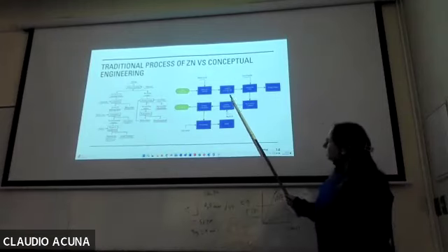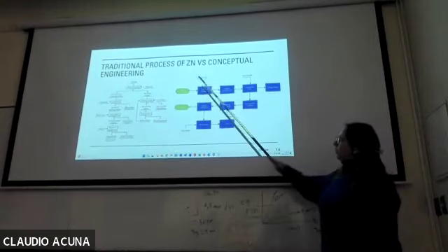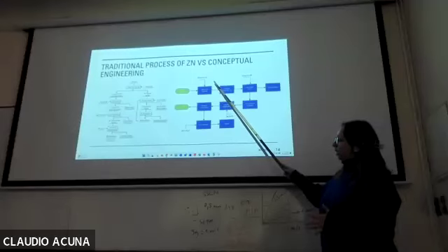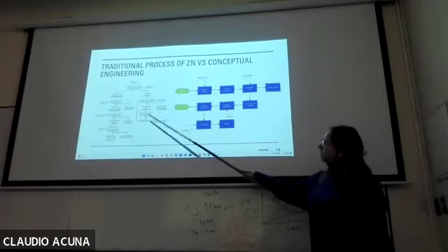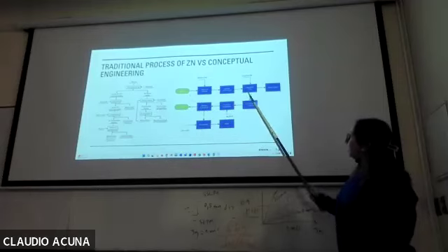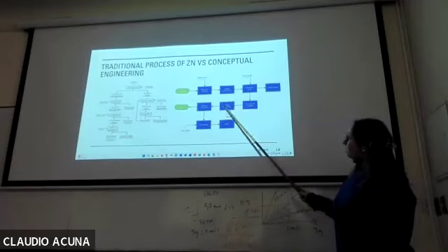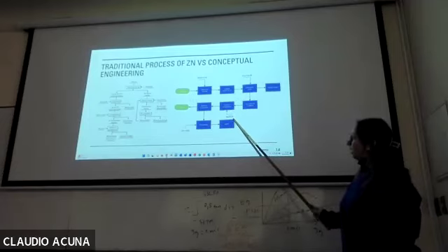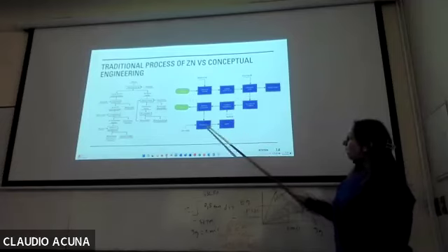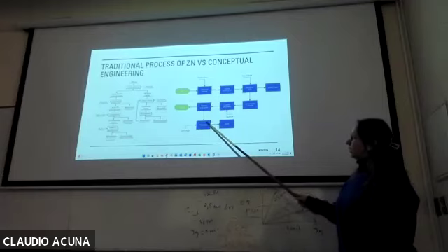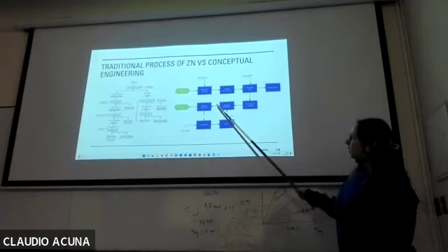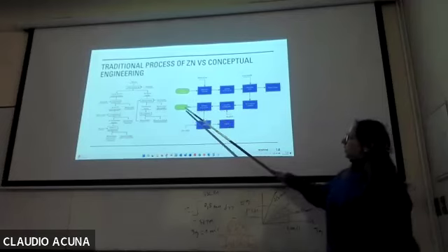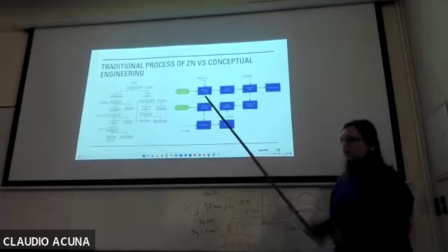On the right side, we have the conceptual engineering we elaborated for this assignment. We have the same process, but we precipitate the zinc and cadmium first with sodium carbonate, and then we have the arsenic in solution that we also treat in another process, but we focus on the zinc and cadmium production.